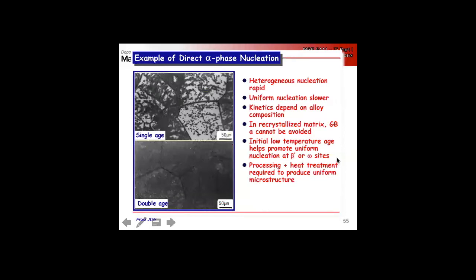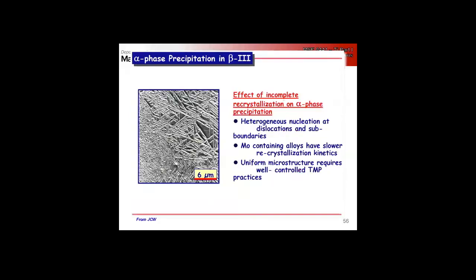So the inclusion of a low temperature age is going to help promote uniform nucleation, both at the beta prime or beta 1 sites or the omega sites, right? And so we're going to have to really make good use of our processing and heat treatment to produce uniform structures. This is just another picture of heterogeneous nucleation of alpha nucleation at dislocations and sub-boundaries.